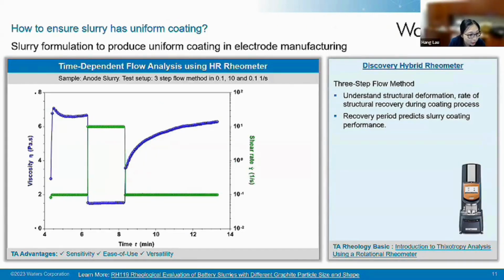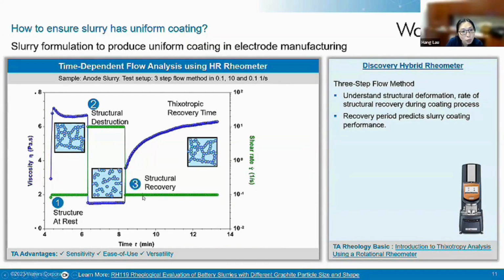In rheology for slurry or coating formulation, oftentimes one big thing that people look into is what we call thixotropy. It is the time and temperature dependence of the slurry behavior. There are multiple ways you can test thixotropy, and the most common way is what we call the three-step thixotropy test. You start with a low shear rate, measuring the viscosity of this formulated material, and oftentimes there is a structure network. Then you go to a high shear rate, shear thinning the material to understand its structure breakdown. And then you go back to low shearing to look at the structural recovery.